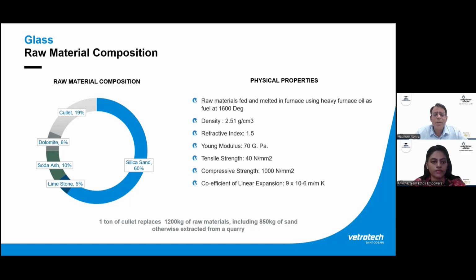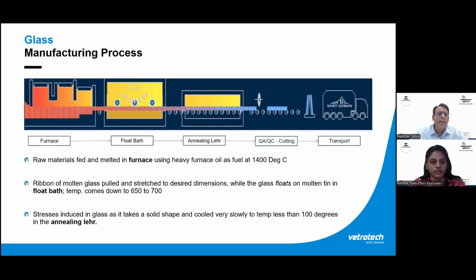But why is cullet used? Because cullet really helps to melt the whole batch of raw material faster. That is why cullet is used as part of that particular batch. If you see the screen now, you will see a pictorial diagram of how the float line looks. We have a furnace where we put the raw material inside and heat it to around 1400 degrees Celsius. Then that whole batch of raw material will melt, and it will go to the float bath, where it will float on the molten tin.